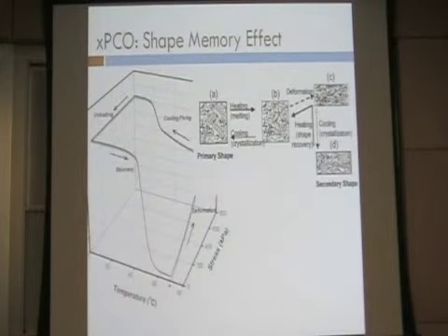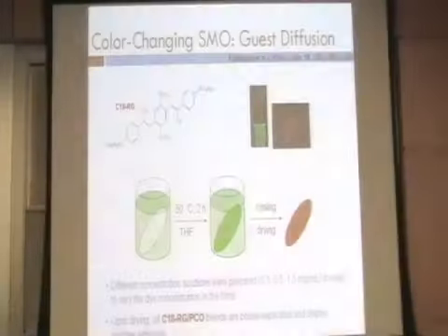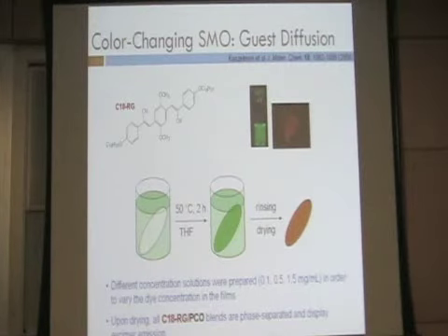And so the idea with this material is that we have a semi-crystalline network that upon heating is an amorphous, disordered, cross-linked material that crystallizes to form a percolating crystalline phase that allows us to keep that temporary state until we heat it. So with Chris Weder's group at Case Western, we decided to combine his dyes that have these long alkyl tails in with our polymer at a very low amount, about 0.1 weight %, and they're partially compatible with our polymer. Our polymer is a solvent for that dye in the melted state, but the moment you crystallize, it does not co-crystallize with the crystalline phase, and so it wants to go to the red state. And so the same phenomenon that drives the shape memory can drive the color change.